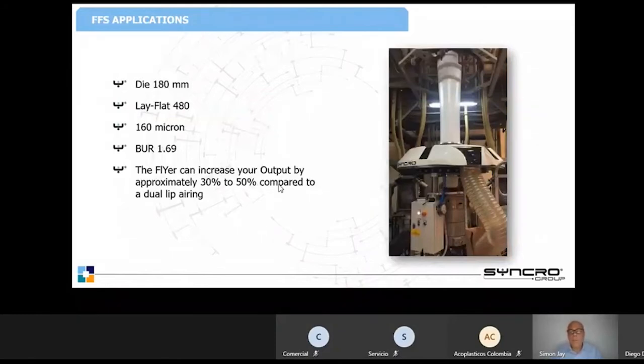Some examples of the products in production. So an FFS application, a die of 180 with a lay flat of 480 millimeters, 160 micron film. Here we would expect to see an increase in output of between 30 to 50%. If you were to supply Syncro your material recipes, they will actually put those output increases as guarantees in writing.